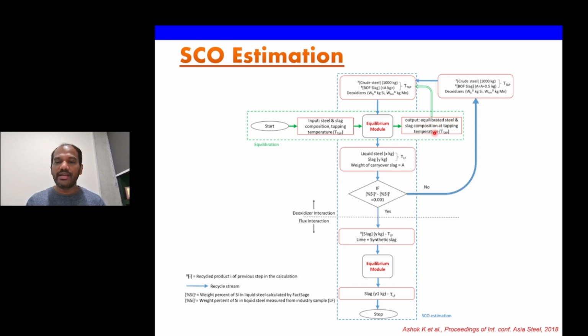Equilibrated steel and slag composition at tapping temperature. This equilibration is essential here because we need to estimate the weight percent oxygen exactly as it is present in the liquid steel, because that is most of the time unknown in the steel industry. For all the inputs, what they generally may know is the final carbon content. So given this carbon content, equilibrating the liquid steel, that is the crude steel, with the slag composition, we estimate the weight percent oxygen present in it.